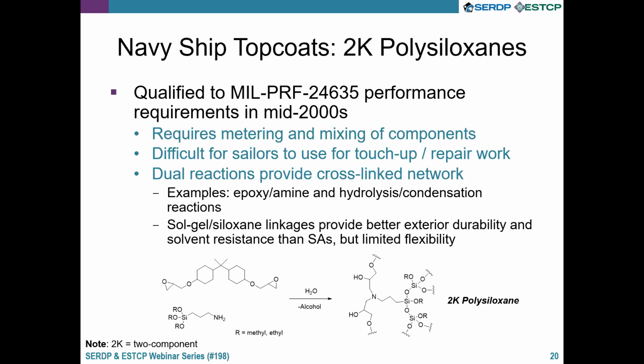These materials are often higher in viscosity than silicone alkyds, and so using them during hot conditions can be problematic. One can imagine, right, you're pier side on the bulkhead of a ship during the summer in, say, Norfolk, where that bulkhead in the sunlight can get up to 110, 120 degrees Fahrenheit. So a coating that may have a few hours of dry time at 75 degrees in the laboratory, that time becomes significantly reduced when it's on a hot bulkhead in the sunlight.